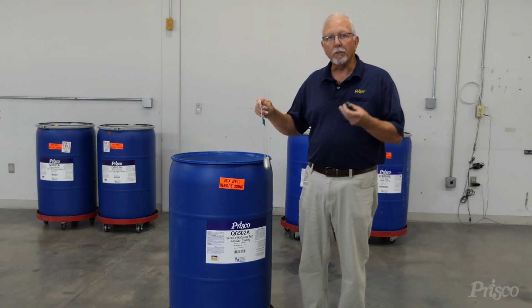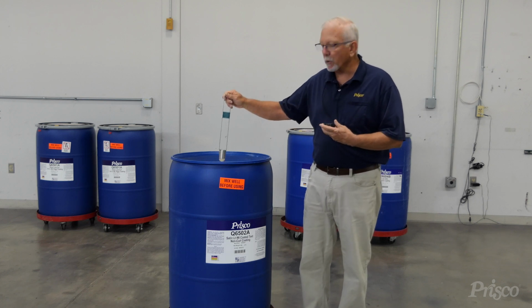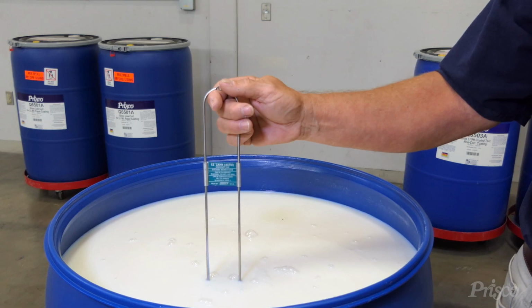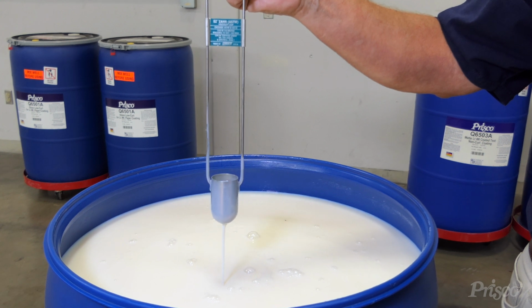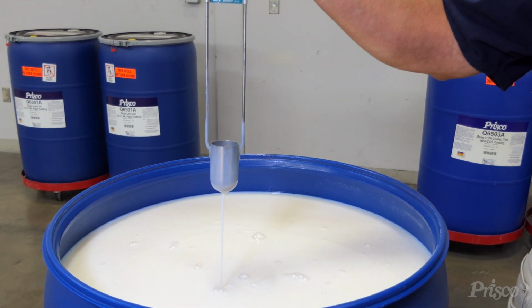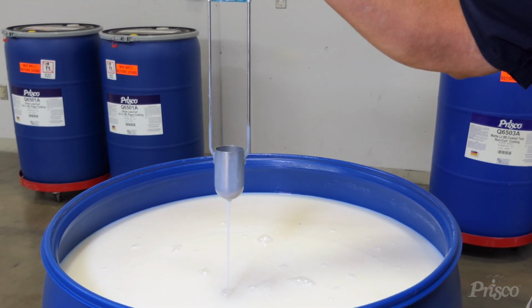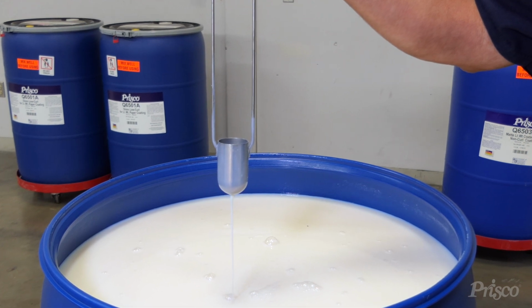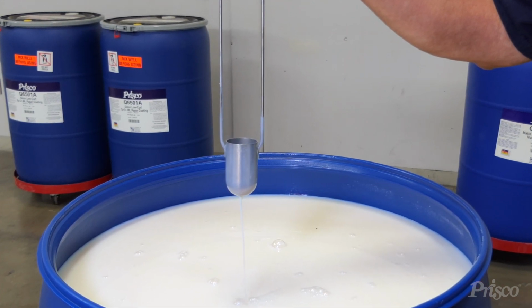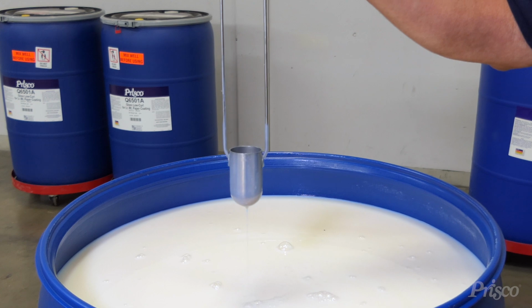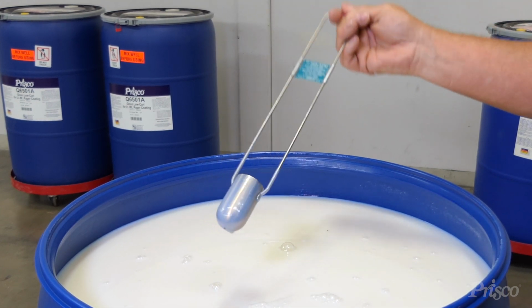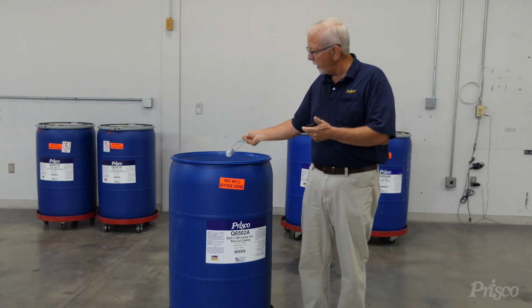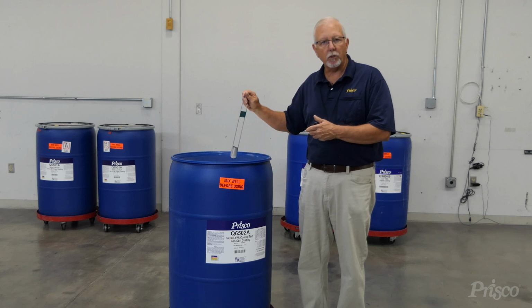To do that, you need a stopwatch. You dip your Zahn cup into your coating. When you pull it out, you start your stopwatch. And as you can see, the coating is coming out in a nice thick stream. But when it starts to break about a quarter inch from the cup, you take your reading with your stopwatch. In this case, it's 15 seconds, which is just where it needs to be.